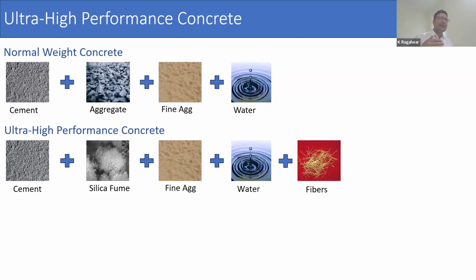So that led to the advent of achieving very high strength up to 30 ksi or 21 ksi. 21 ksi means 150 MPa. So when newer concrete materials, which were known as ultra high strength concrete, started reaching these high strengths, they also realized that towards failure, the failure is very sudden and catastrophic. So basically at higher strength, there is no post-peak behavior in ultra high strength concrete. As soon as the concrete breaks, it just disintegrates into fragments. So they started adding fibers into that to have some kind of post-peak slope to it. And later on, they realized with experiments that these fibers not only contribute to a post-peak compressive behavior, but also help in some kind of tensile strength.